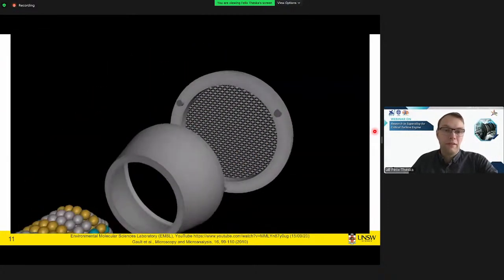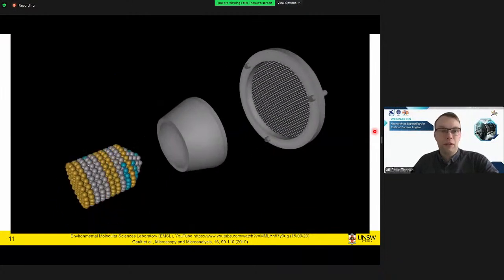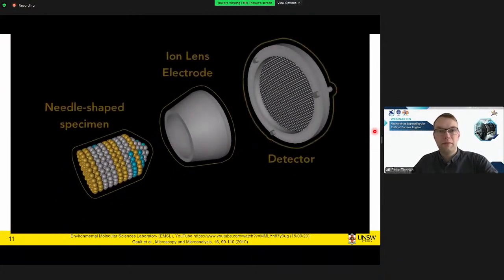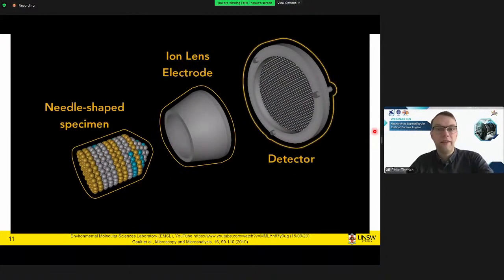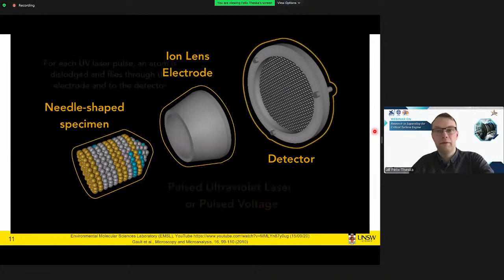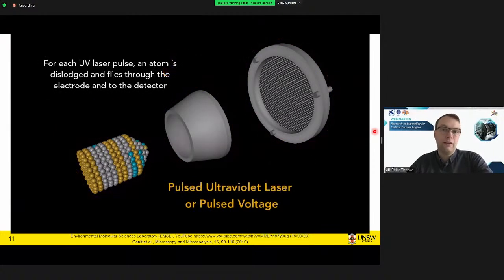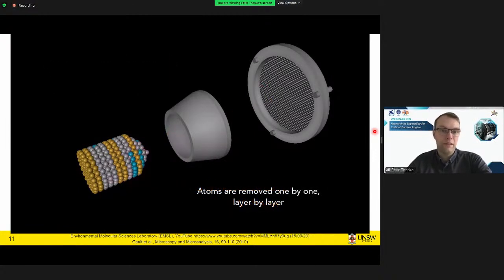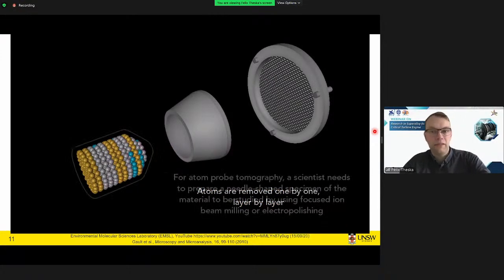So in this nice animation, we see we need a very sharp needle-shaped specimen, which is placed in front of an ion lens or local electrode. After this local electrode, we have a 2D detector. And then we can detach individual atoms by laser or voltage pulsing. And these atoms are ionized and then accelerated towards the detector screen.